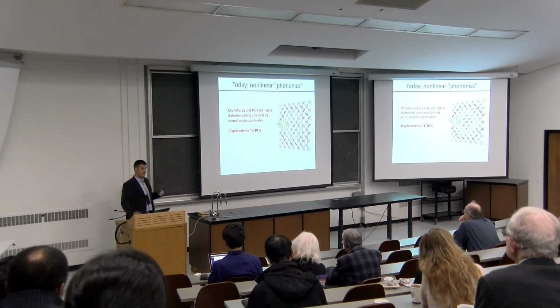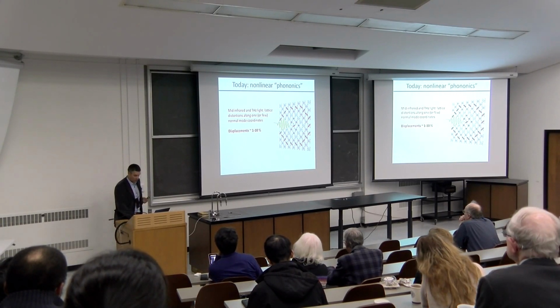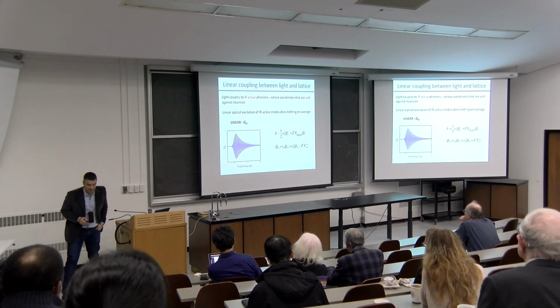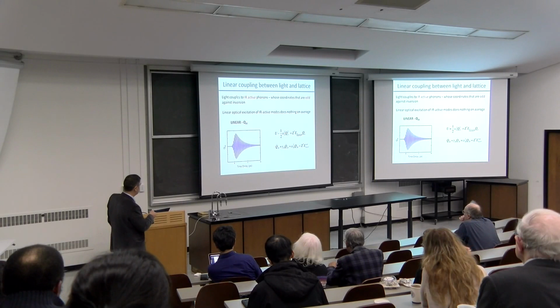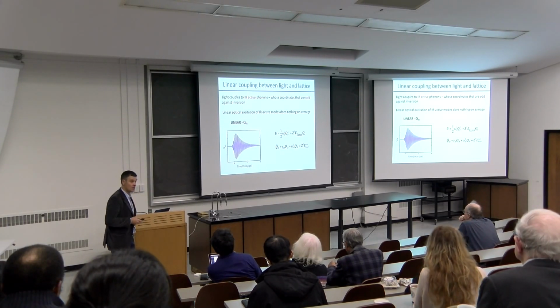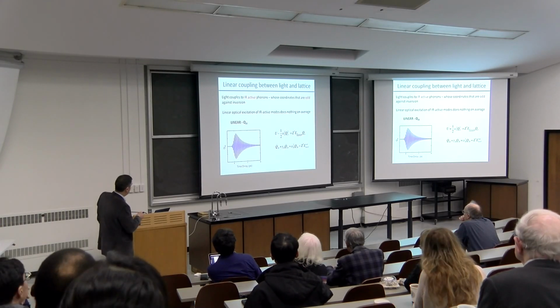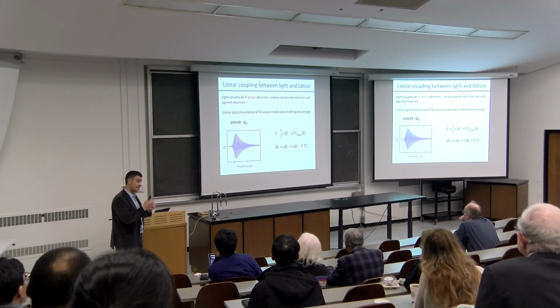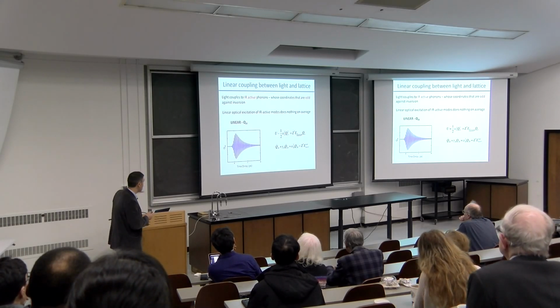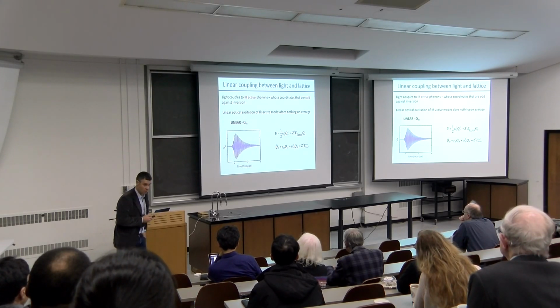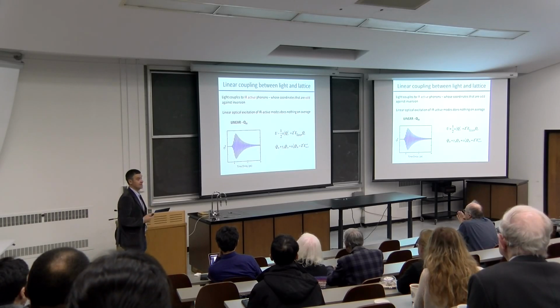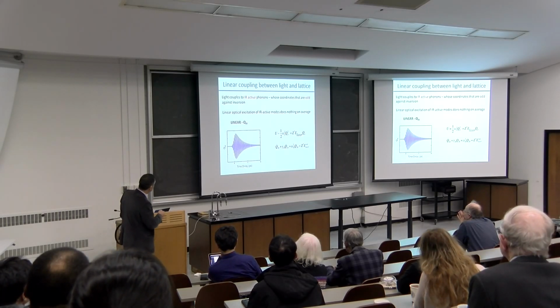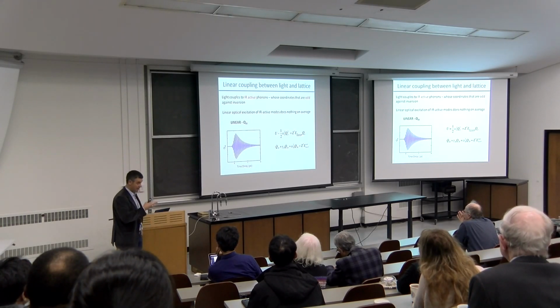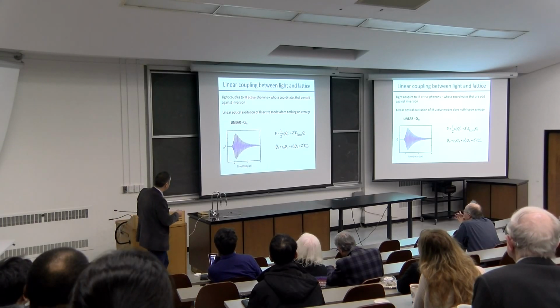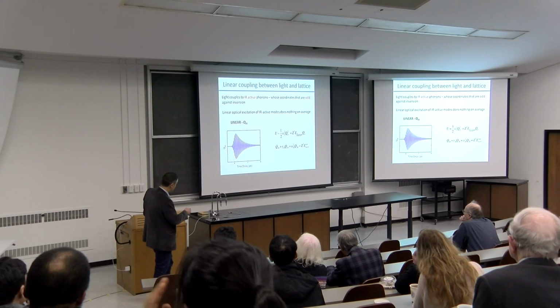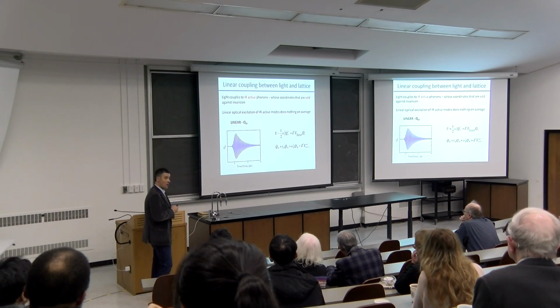So before I get into nonlinear phononics, let's go back a second and reflect on how we understand linear phononics. As I mentioned, light couples to infrared active phonons, which means that their coordinate is odd against inversion, and also those with bonds that have a significant amount of charge, and this is determined by a particular tensor, which is called the Born effective charge. It's a tensor that tells you how much charge I have in each one of these phonons. And if I think about the excitation of a phonon with light, I can think about basically a damped harmonic oscillator. A phonon in a laser field can be discussed in terms of the energy of a spring, which is proportional to the square of the generalized coordinate.